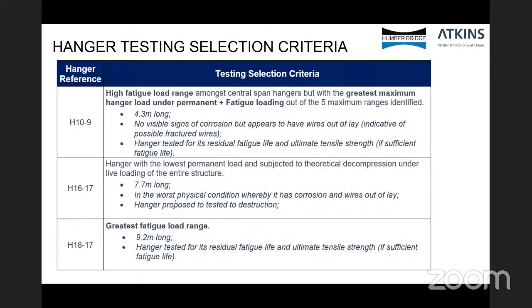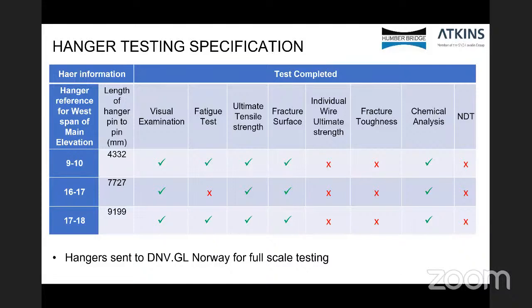Hanger 18-17 was 9.2 meters long. It had the greatest fatigue load, and again, it was proposed to test this to fatigue loading and ultimate tensile strength. If you go on to the next slide, please. This just really shows an overview of what testing was to be completed: visual examination, fatigue testing, ultimate tensile strength, fracture surface examination, chemical analysis.